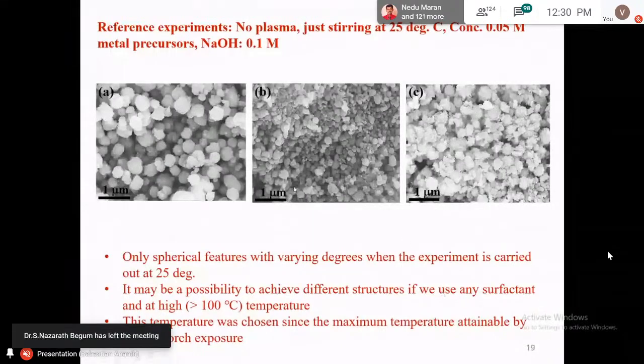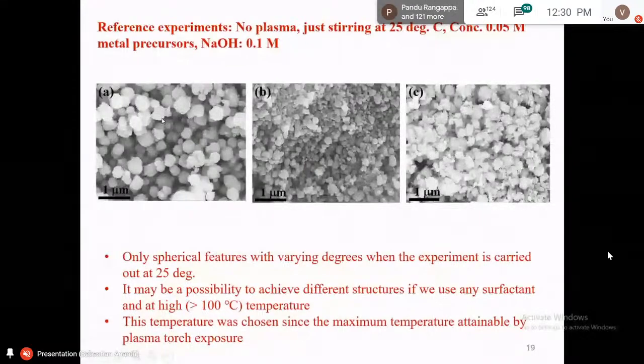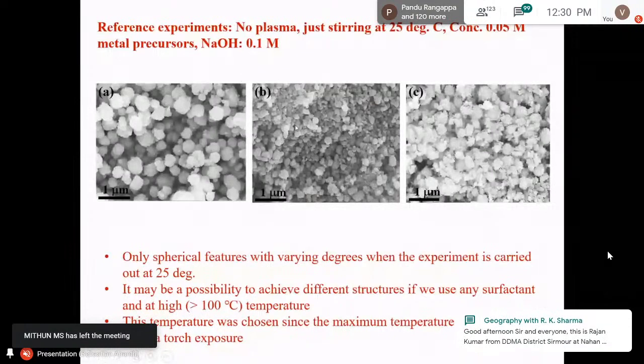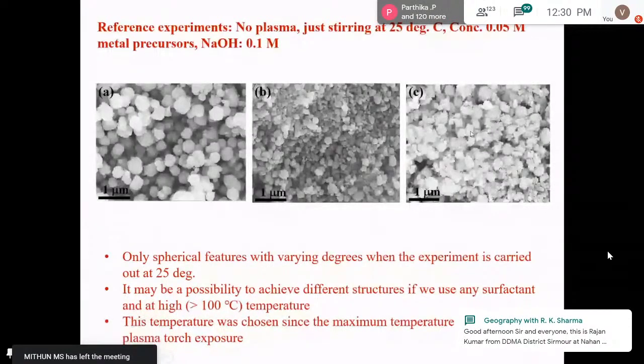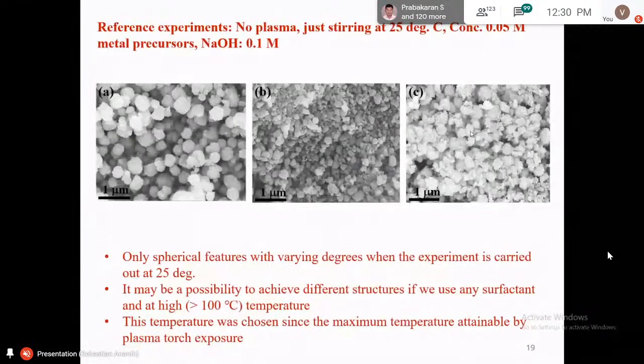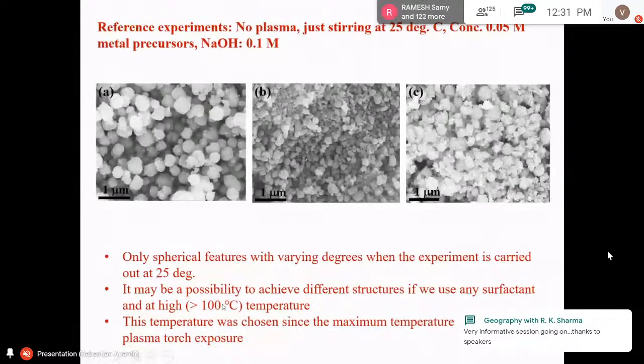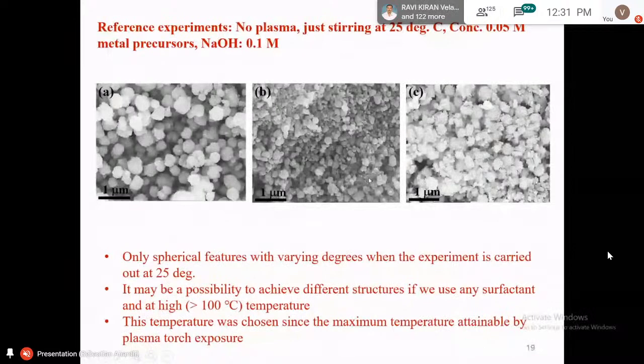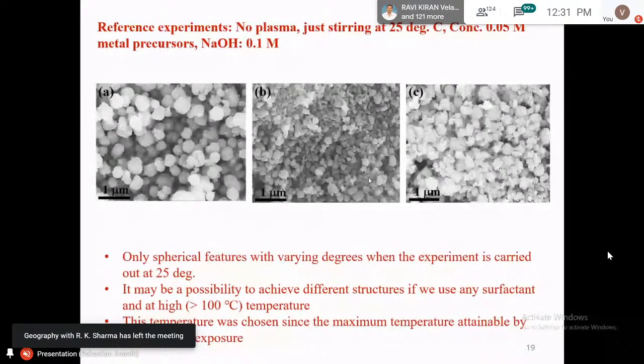Okay, first of all, these are the surface morphologies of zinc oxide prepared using zinc nitrate, zinc chloride, or zinc sulfate without applying any plasma or any temperature or any surfactant. It is just prepared at normal room temperature. So what happened? Only spherical surface morphology was obtained for zinc oxide. Suppose we use a very high temperature, there may be a possibility of getting some other structure, or if we use some other technique, we will get a different morphology. But if we do not use any surfactant or temperature, we will get this structure.